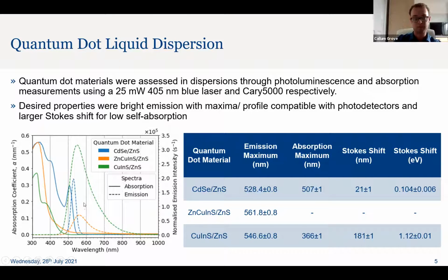And the ideal quantum dot characteristics that we were looking for, in selecting the one to load into a plastic scintillator, was bright emission. And so the brightest emission came from our copper indium sulfur with a zinc sulfur shell, compared to the cadmium selenium, and then the even dimmer zinc copper indium sulfur.